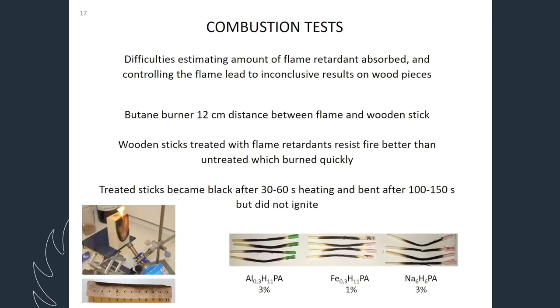Now the combustion test of the wood. As I mentioned earlier, the amount of flame retardant was a bit difficult to estimate with the wood samples, because of the difference in humidity when we prepared the samples.